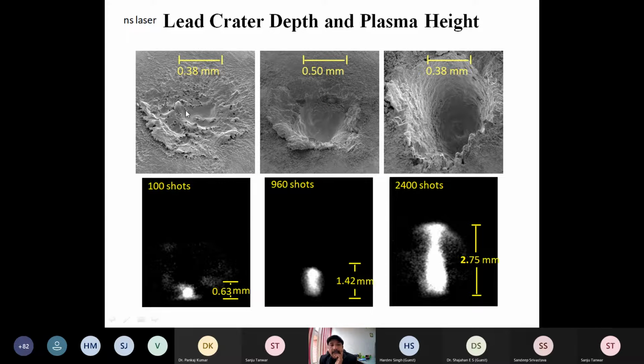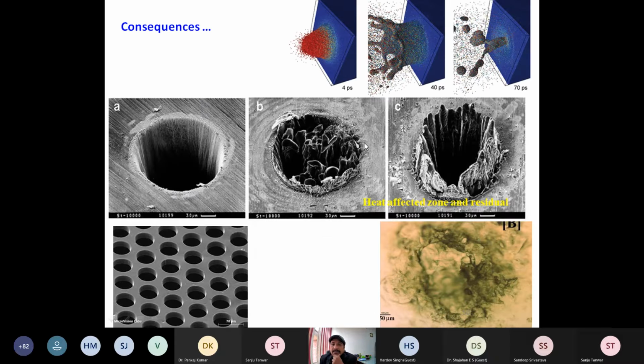One example here, if you use a nanosecond laser, you can see that with 100 shots the structure is something like this, while with 2400 shots it is much deeper. However, outside the circumference of this structure you can see that there are some residuals, so damage is more in case of nanosecond. So this is just for the comparison.